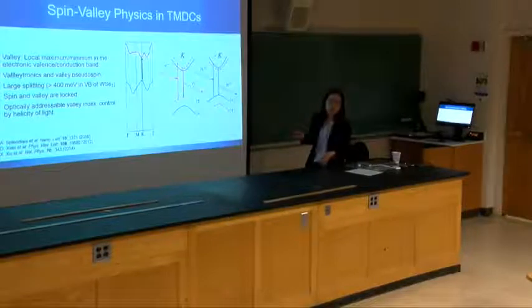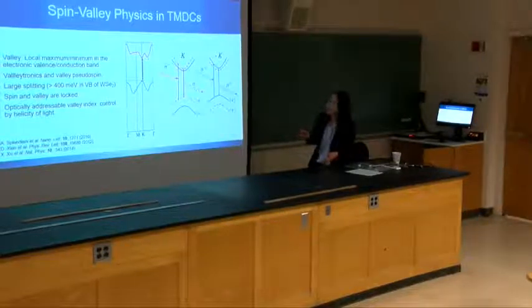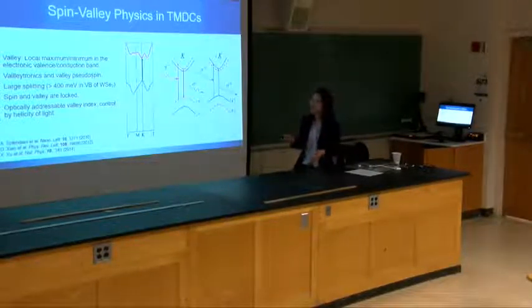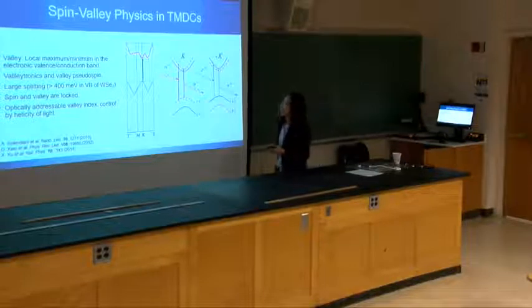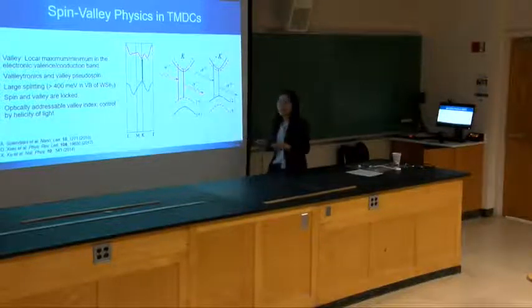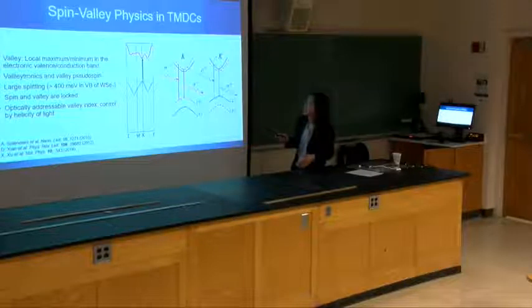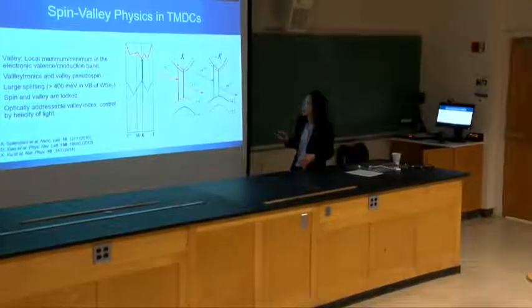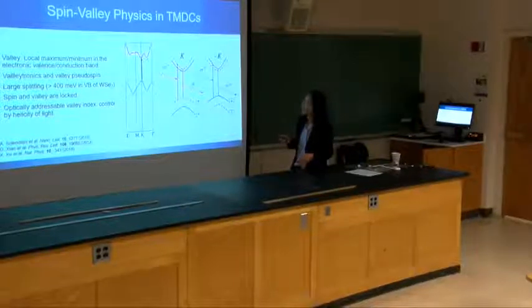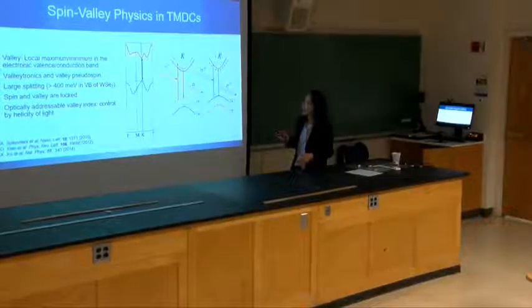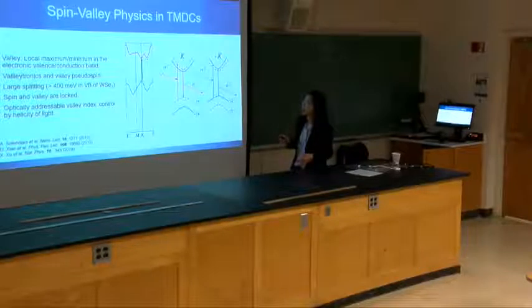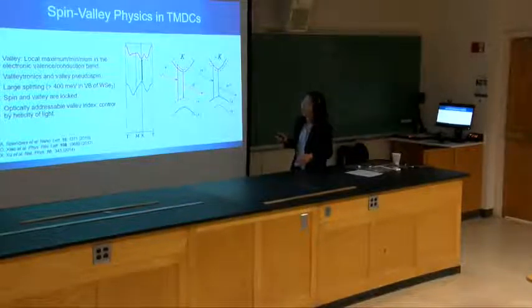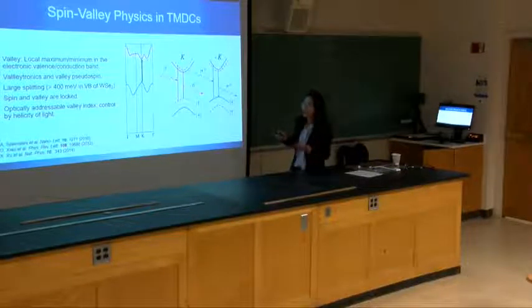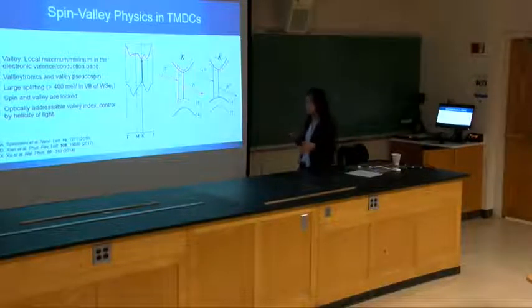Another interesting property of this spin valley physics in transition metal dichalcogenides is that the valley index can be addressed by light. Light with different helicity, sigma minus and sigma plus, talks to different valleys. For example, the K valley only emits and absorbs sigma minus polarized light. If we shine sigma plus polarized light on the K valley, it will not talk to it. There's no interaction at all.